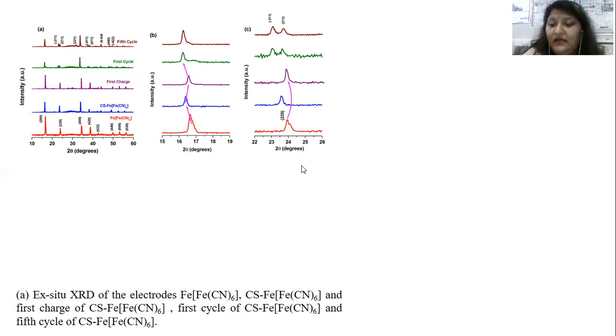You can see that the high intensity 200 peak shifts to a lower angle upon chemical sodiation of FeFeCN6, which is an indication of lattice expansion, followed by a high angle shift during the first charge, which is due to lattice compression upon desodiation. The lattice expansion happens again when sodium is inserted back at the end of the first cycle, along with the phase transition. A similar observation was found in the 220 plane also.